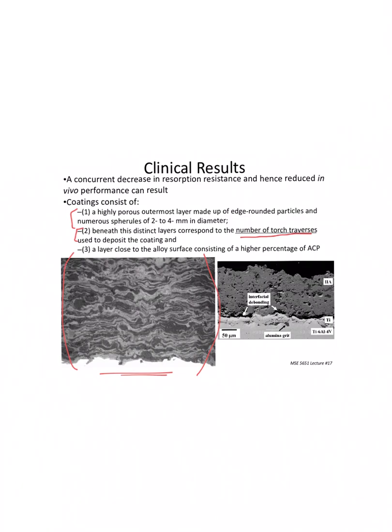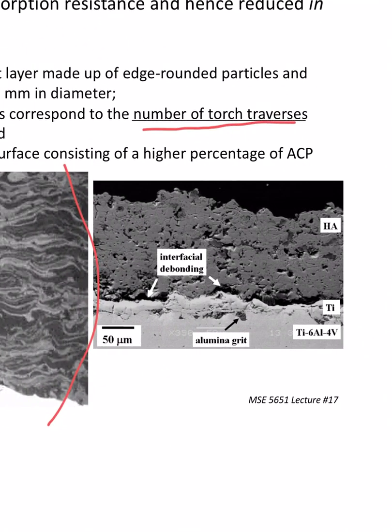But then where things can go horribly wrong is where we have produced our HA coating. From the outside it looks good. It's on Ti 6-4. That's wonderful. But you have this interfacial debonding when the amorphous calcium phosphate dissolves out. Okay, so that means that there's a weak point where you want it least. All right, so this could be sheared and perhaps peel off, and then you don't get your bone ingrowth because hydroxyapatite is no longer associated with the implant itself. All right, any questions about that? Hopefully it's pretty straightforward.